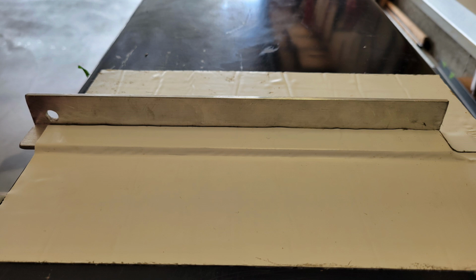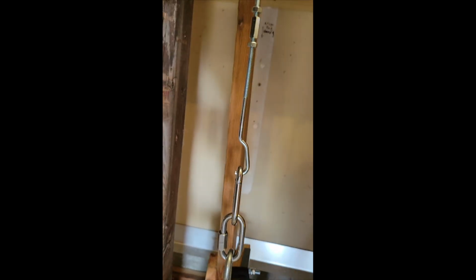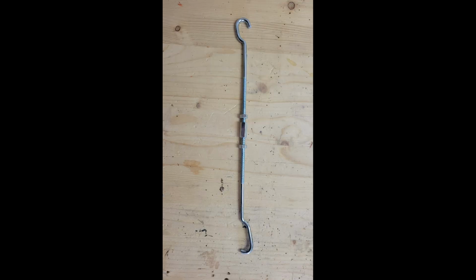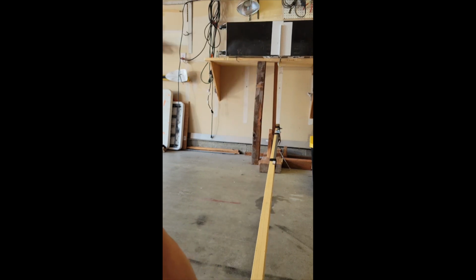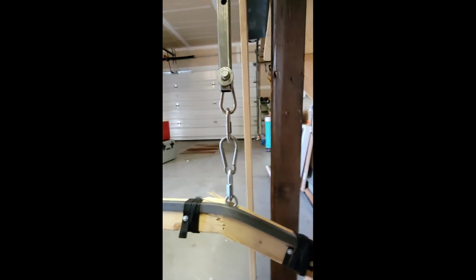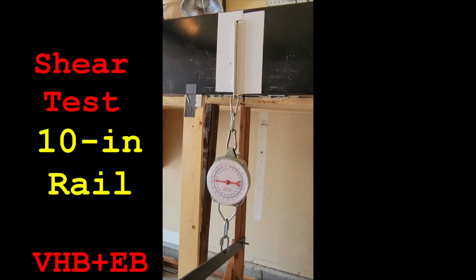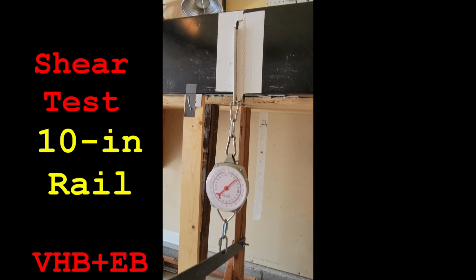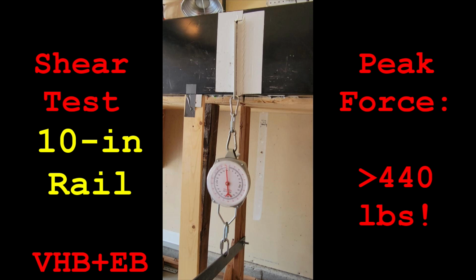It has 10 inches of VHB tape, 1 inch wide, and Eternabond tape along both sides of an aluminum angle section. To make a long story short, I broke my rig 4 times trying to pull that rail off. After repeated pulls, which probably weakened it, I pegged the scale and the rail finally came off. So at least 440 pounds force per 10 inches of rail, probably closer to 500 pounds to pull that sucker